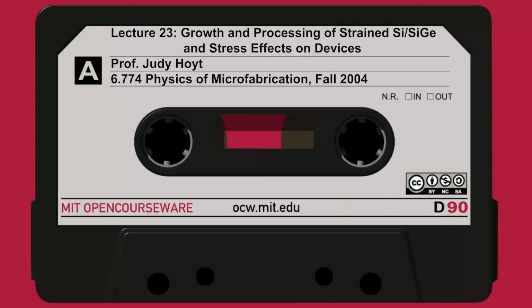You can also do bonding and hydrogen-induced delamination, or Smart Cut. If we've studied Smart Cut for silicon, here we start with a relaxed silicon germanium epilayer. We ion implant with hydrogen, and at the peak of the hydrogen, bubbles form. So after we've done the bonding, we heat it up, and those bubbles end up cleaving it off. You get the delamination process. This is exactly analogous to what happens in SOI fab, and now you have silicon germanium on insulator.